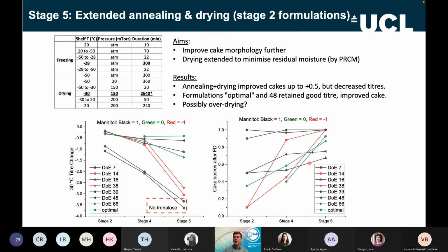And if we were focusing on the cake score, that was getting progressively better, so the logic was paying off, and all of our formulations were improving in cake score. But you can still see we had this issue with trade-off, where many of the formulations were nosediving into really poor titer losses, although what we called the optimal formulation, which was the predicted optimum from our DOE, was actually still quite robust, so we could get a good cake improvement and retain the same titer. So hopefully we're able to beat the trade-off with some of our formulations in these conditions and this process.